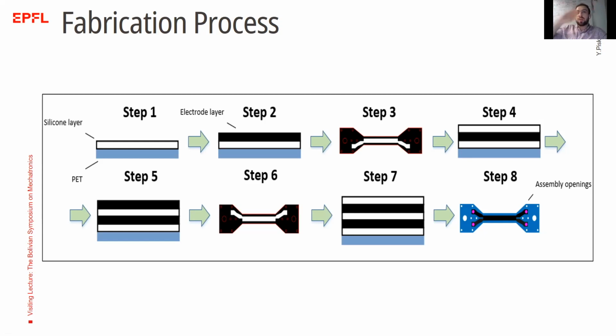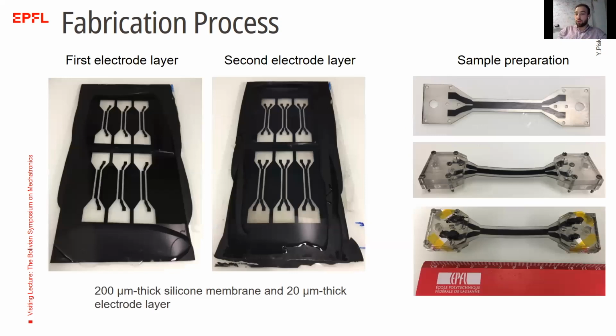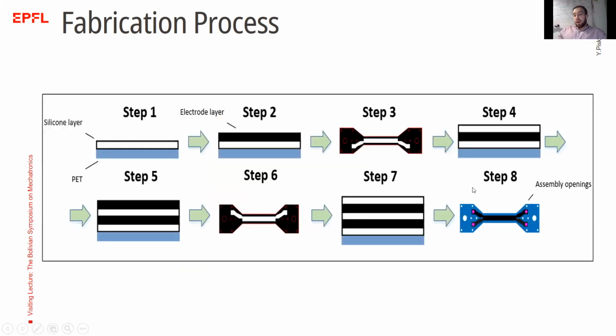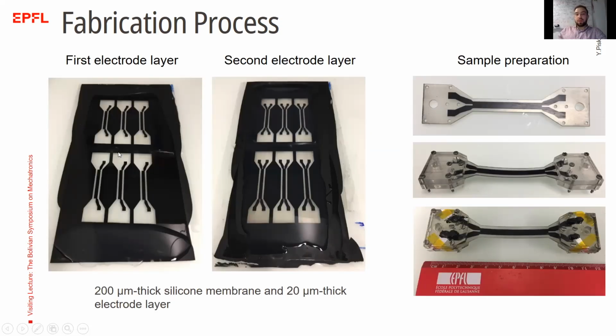So we remove some of the conductive silicone. Let me show you how it looks. Look at this picture here. What you see here is a structure composed of 3 layers. It's a silicone layer, a conductive silicone layer, then we etched one of the electrodes with this V shape on one end. And then we put one more silicone layer. So let me go back. That's actually what I showed you. Step 4 is equal to this picture here, right?